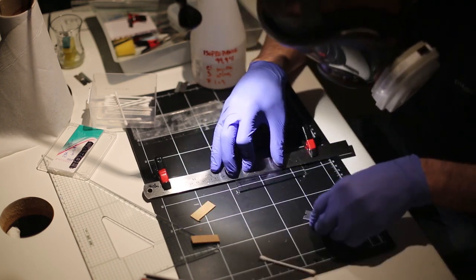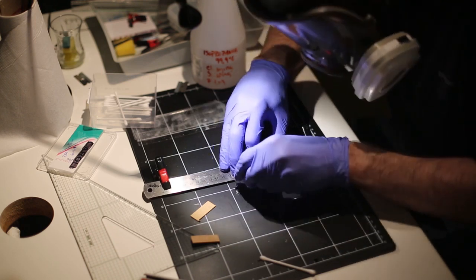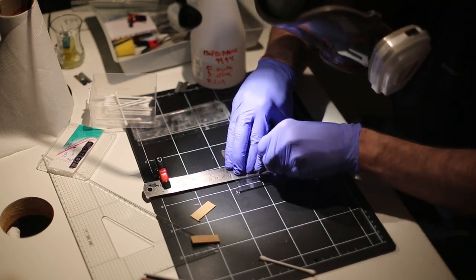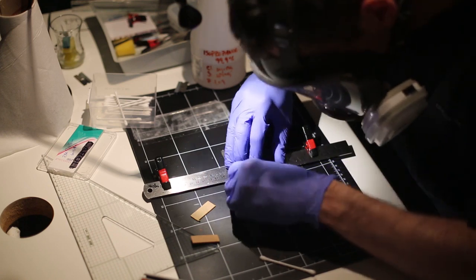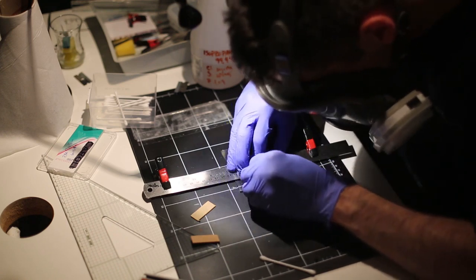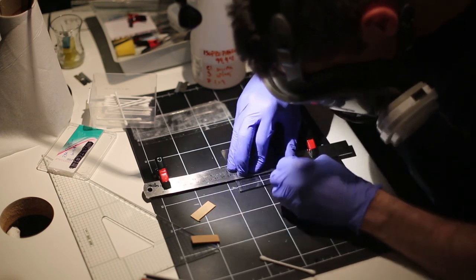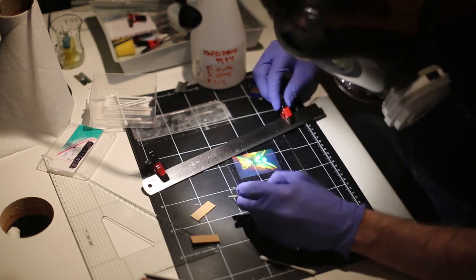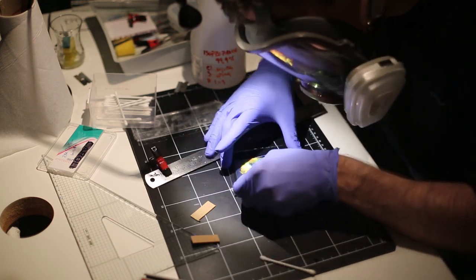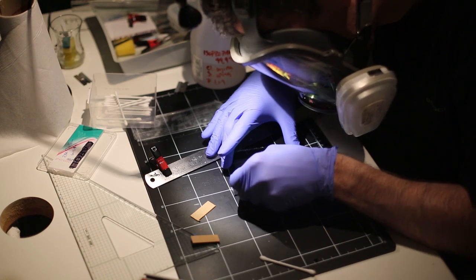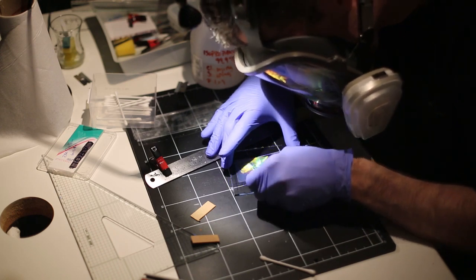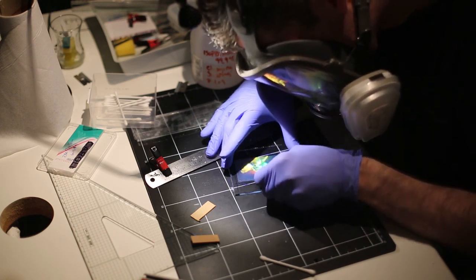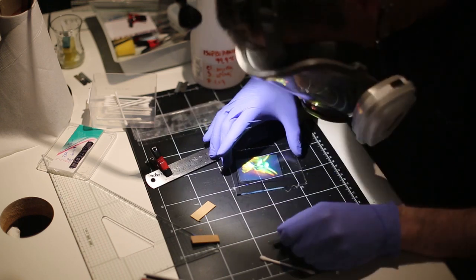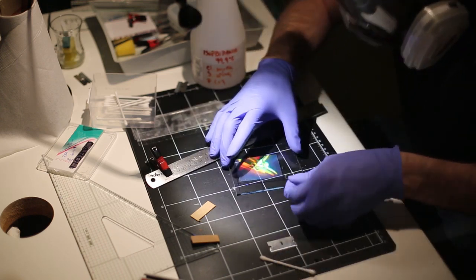Now I prepare for the final cut. Once again, I swipe the emulsion with a cotton swab dipped in alcohol. I use a new razor blade and cut the emulsion on the marked line. With the flat part of the razor blade, I take off the final strip. By leveling the razor blade flat and hitting the cut in a knocking motion, I can remove even the smallest residue of gelatin from the plate.